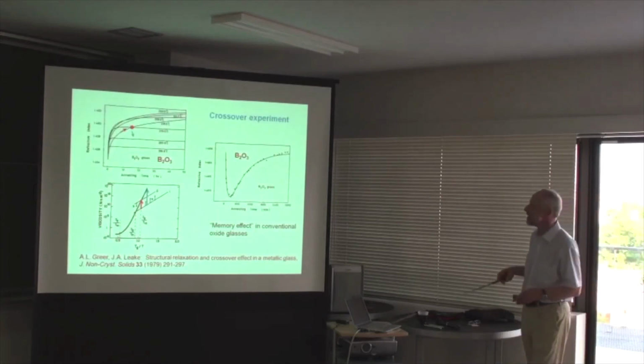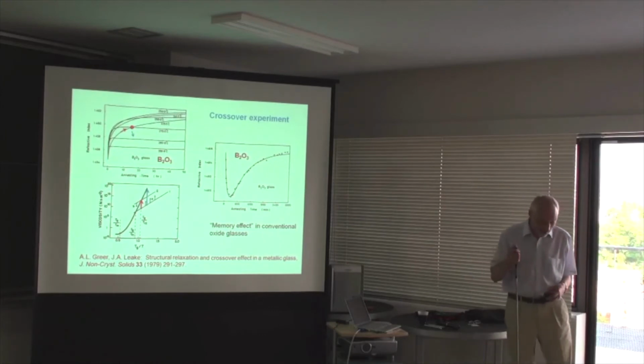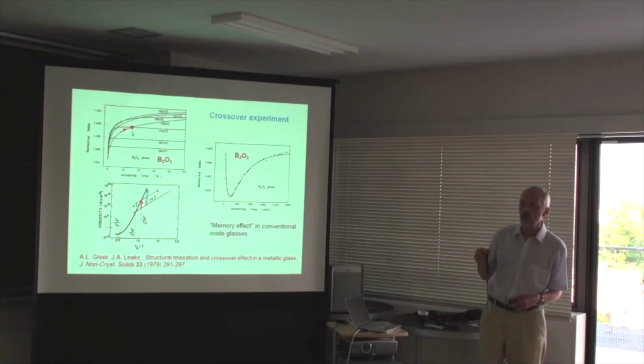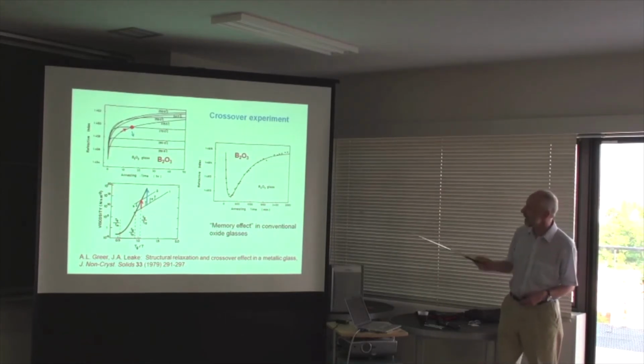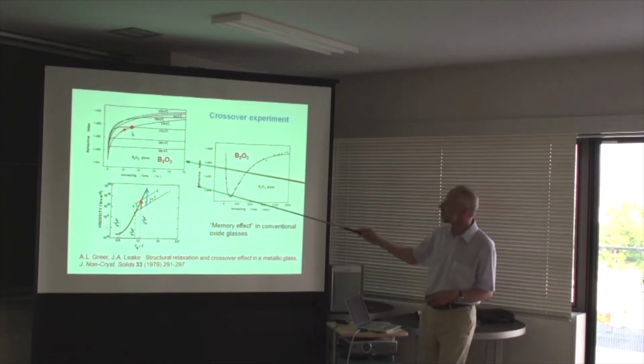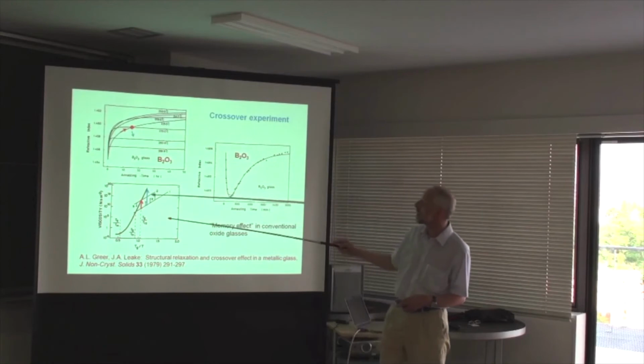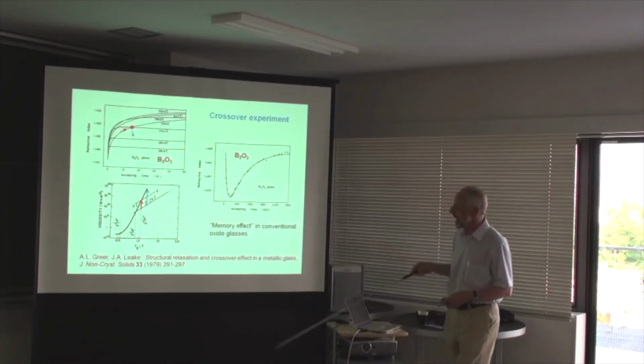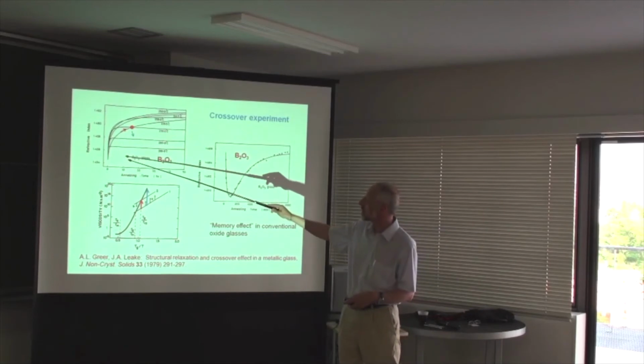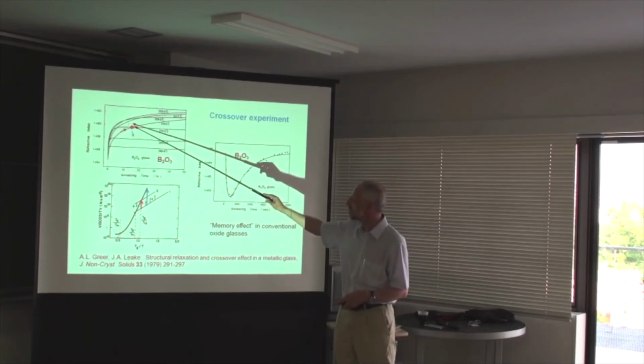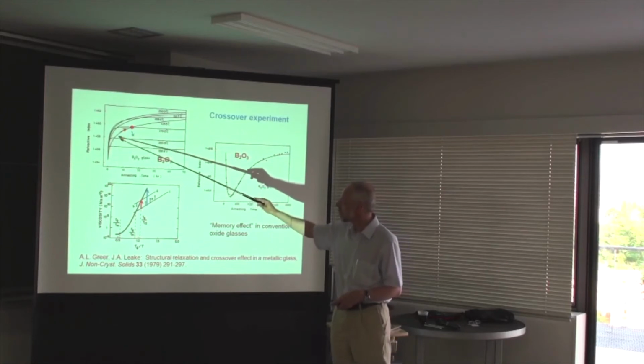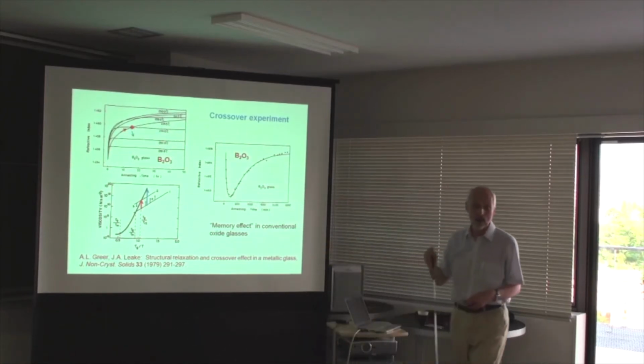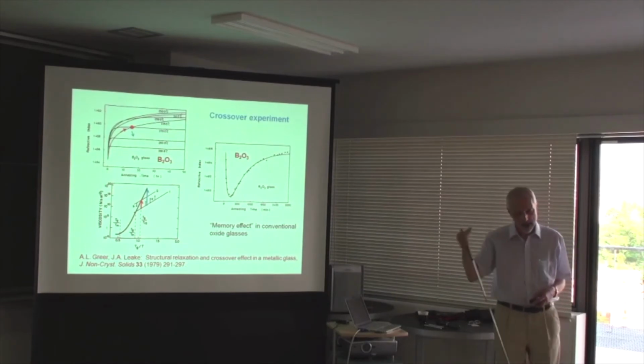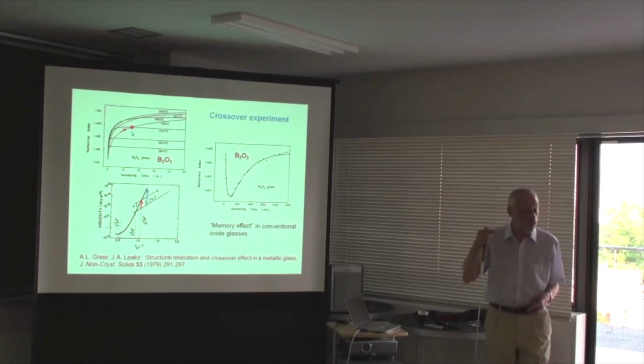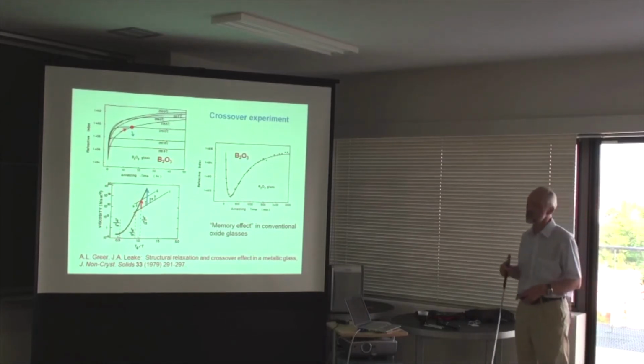When I was doing my PhD, these are figures from my PhD, it was still in some way not quite respectable to think that metallic glasses were glasses in the ordinary sense. And I could realize that oxide glasses show phenomena called relaxation, where a property, in this case the optical refractive index, changes with heating, and it changes differently at different temperatures, and you can get this situation where heating it at a high temperature could bring you to that point, heating to a low temperature could bring you to the same property value, and you would normally think that those two samples, heated at different temperatures, but with the same value of a property, would have the same structure. And it turns out they do not.